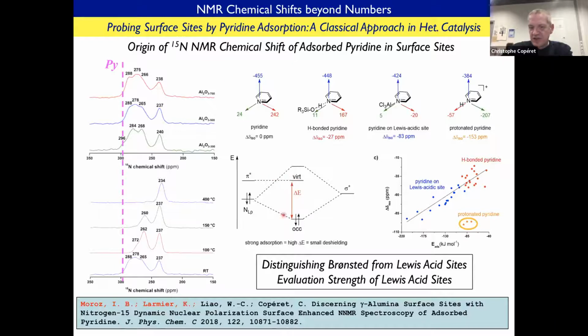It turned out that the chemical shift is directly related to the difference of energy between this new bond and the empty pi star orbital on the aromatic ring. And there is a direct relation between the chemical shift and the adsorption energy of that molecule on the surface. So you can actually relate thermodynamic enthalpy with chemical shift. So again, chemical shift is a very, very important tool to understand not only chemical reactivity, but also surface species and relate them to acidity. Let me finish with one last example.